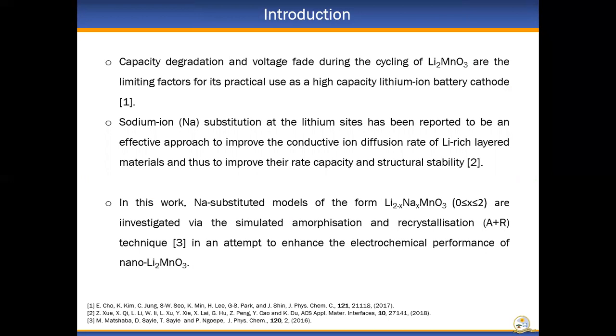its practical use. Studies have shown that sodium substitution at the lithium sites of this material can be an effective approach to improve lithium ion diffusion, to stabilize the structure, and also to increase the rate capacity. In this work, sodium substituted models were generated by the simulated amorphization and recrystallization technique in an attempt to enhance the structure and electrochemical performance of the Li2MnO3 cathode.